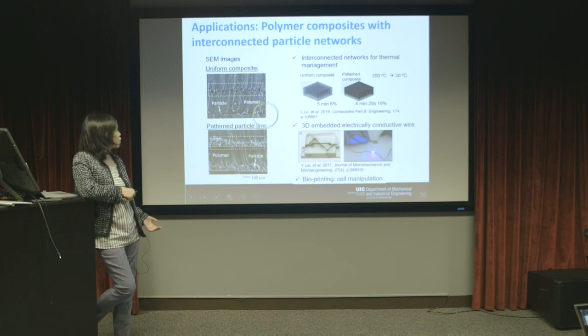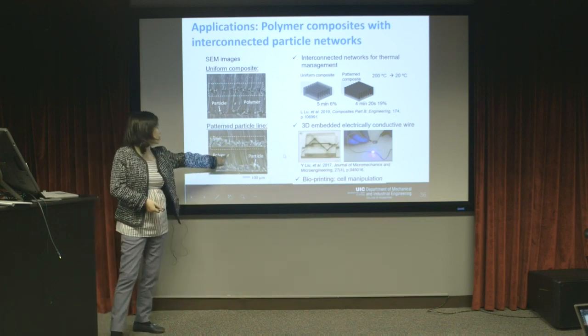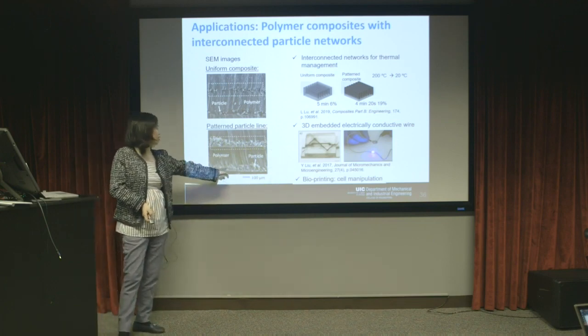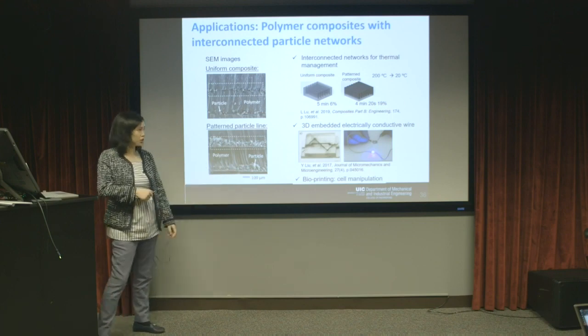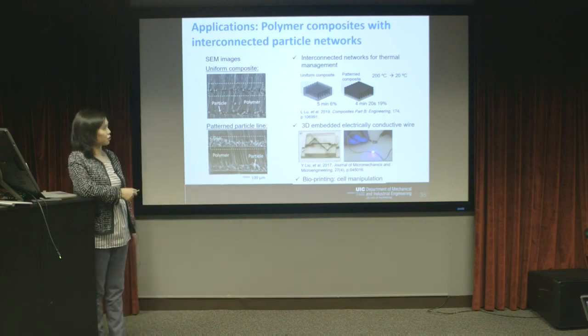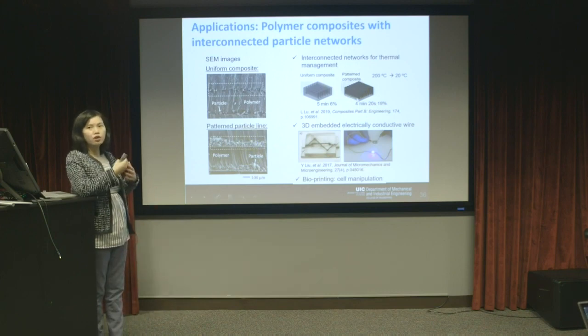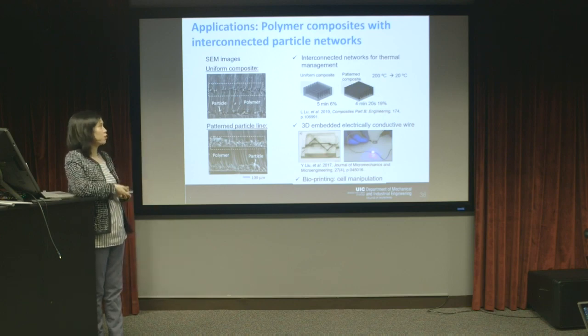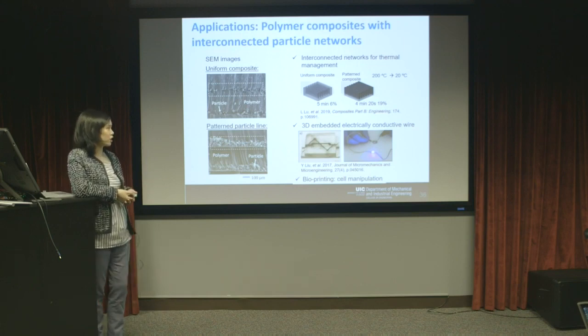You can see that in the uniform composite, particles are uniformly dispersed in the polymer matrix. In the patterned particle lines, some regions are almost pure polymer, and it has connected particles between the layers. In this way, you can form thermoconductive lines or networks inside the part, or even 3D networks for thermal management.